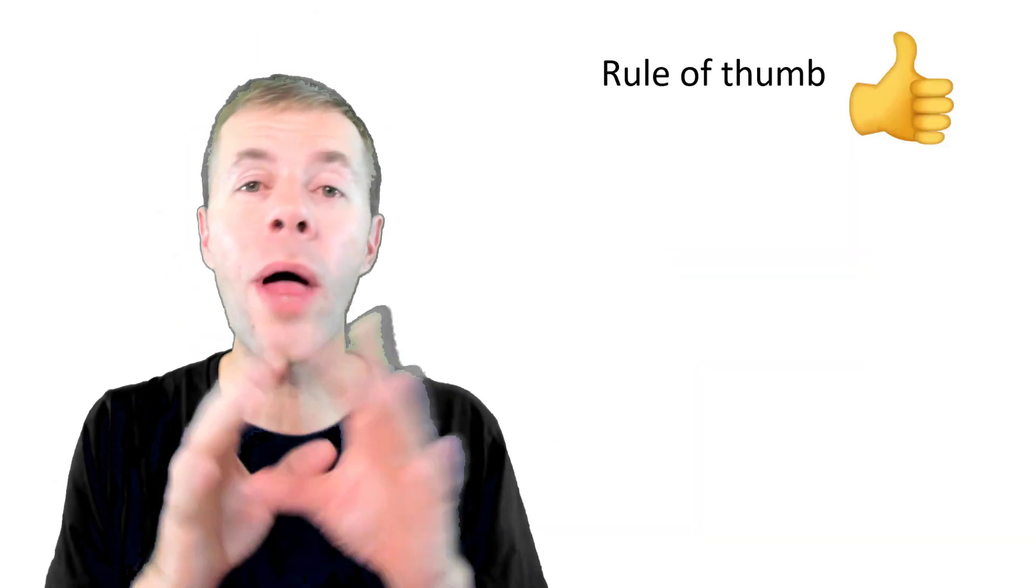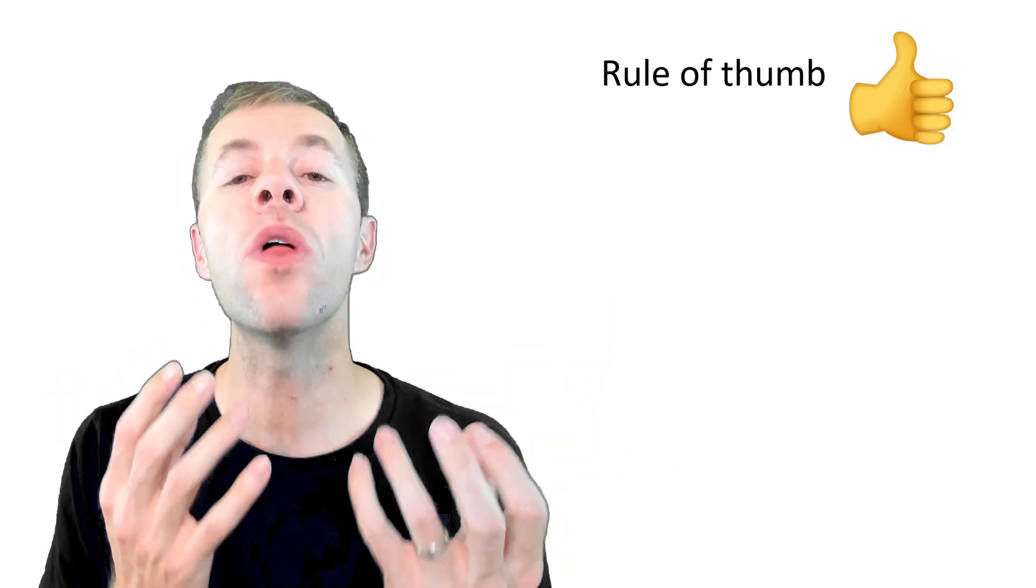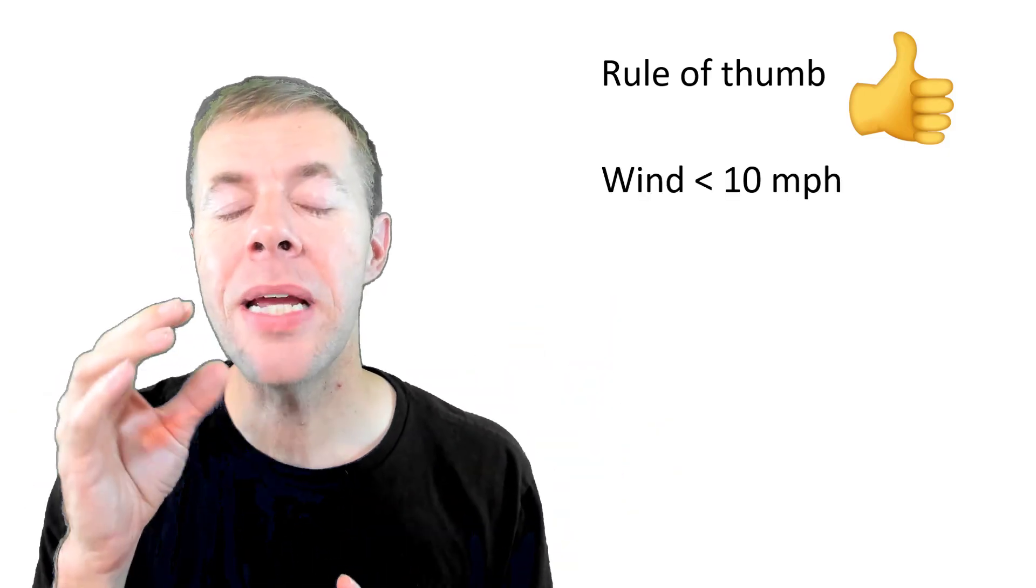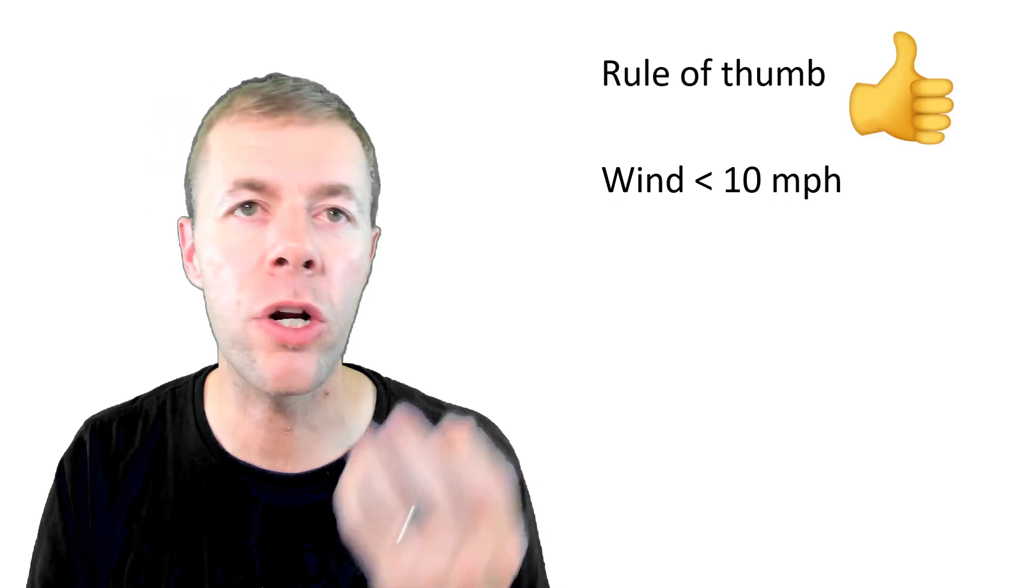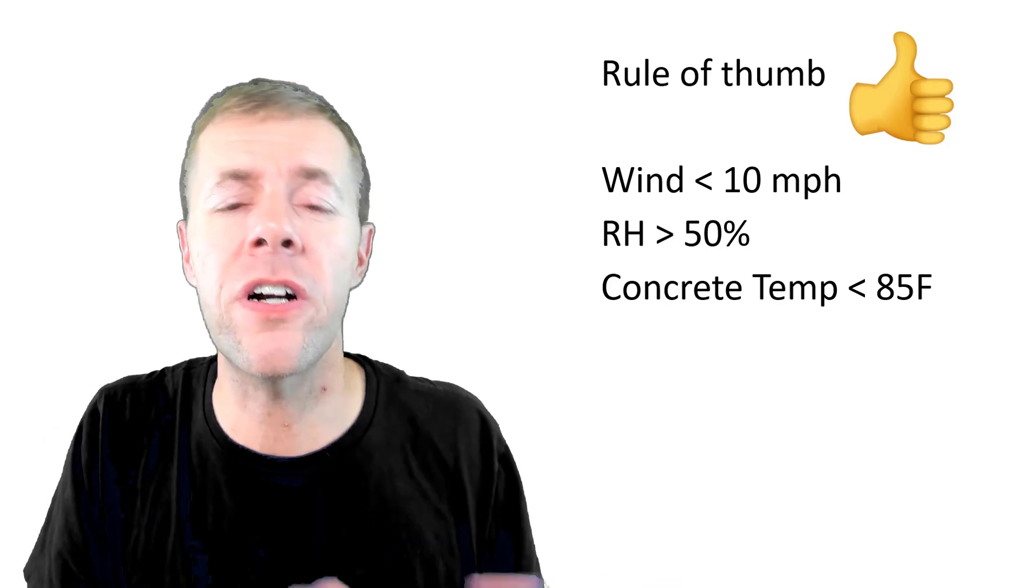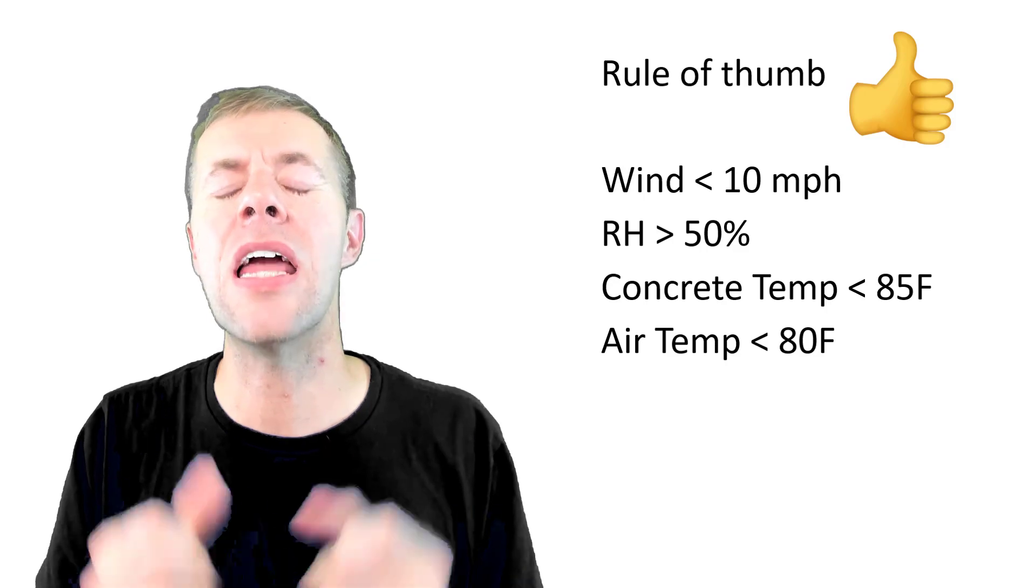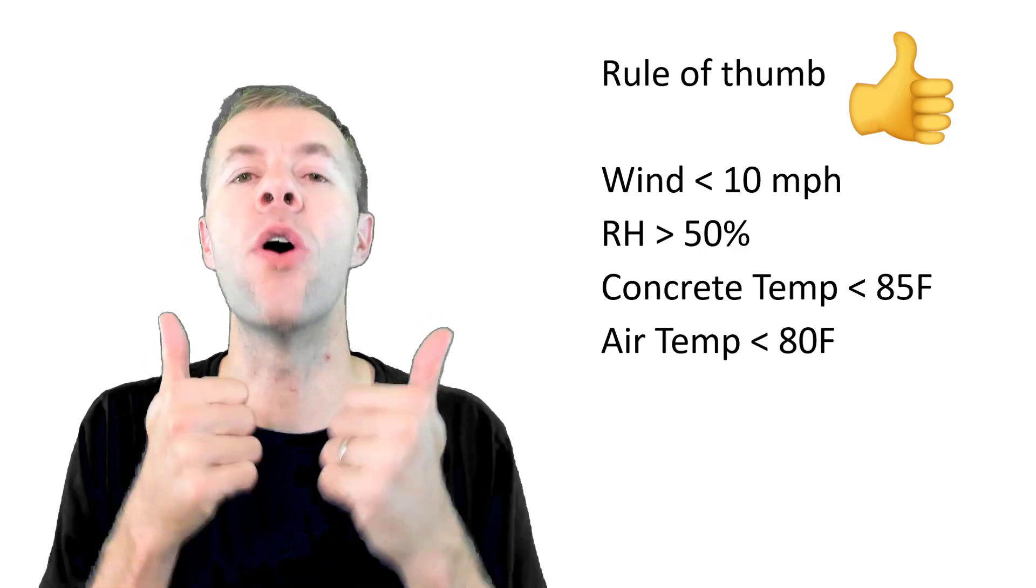But a rule of thumb, if you don't like math, graphs, or nomographs: if your wind speed is less than 10 miles per hour, your relative humidity is above 50%, your concrete temperature is below 85 degrees Fahrenheit, and your air temperature is less than 80 degrees Fahrenheit, you are gonna be okay.